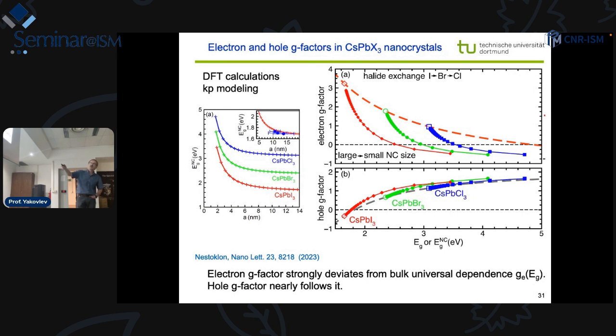Now we can change the energy in different ways. For example, we take a cesium lead iodide nanocrystal, a very large nanocrystal, which would be here at the bulk value. Now we reduce the size of the nanocrystals, so the confinement energy changes and we increase the energy due to confinement. The first expectation is that we should follow the bulk trend, but it's not working. The theory predicts a much stronger dependence for nanocrystals, cesium lead bromide or chloride. For the electron g factor, much stronger changes are predicted due to the mixing of the spin-orbit bands. But for the hole, the theory predicts very weak changes.